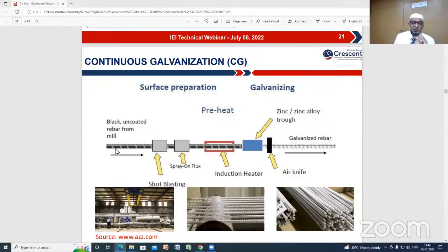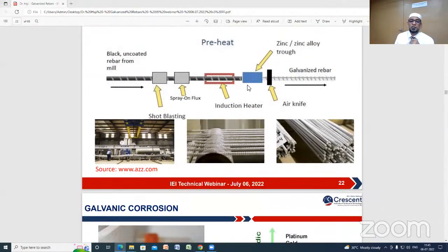Now here, after the manufacturing of the conventional steel rebar in the steel plant, it is subjected to shot blasting to make the surface of the rebar a bit rough. Then flux is applied. Then it is heated to 450 degrees centigrade. In the earlier batch process, the rebar is dipped in molten zinc. Here, the rebar is heated to 450 and then passed through the zinc alloy trough. Then they have some measures to control the thickness, and you will find the galvanized rebar. I also visited this unit. It takes around 15 to 20 minutes to complete all the operations. So the advantage in this process is that you get the galvanized rebar from the steel manufacturer itself.